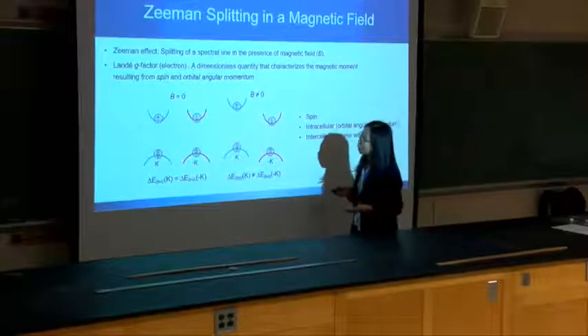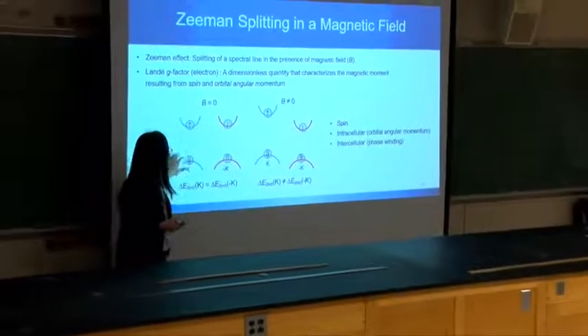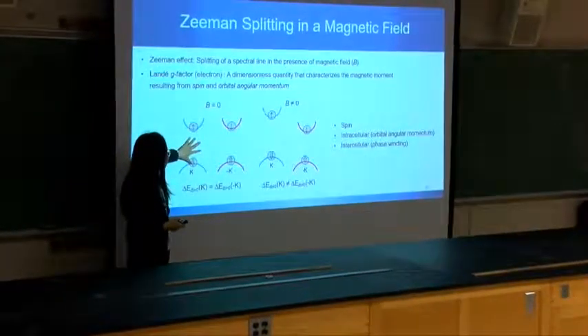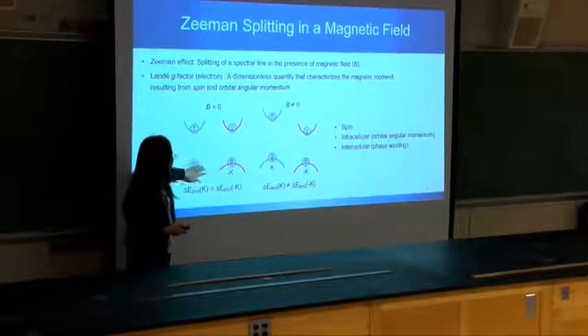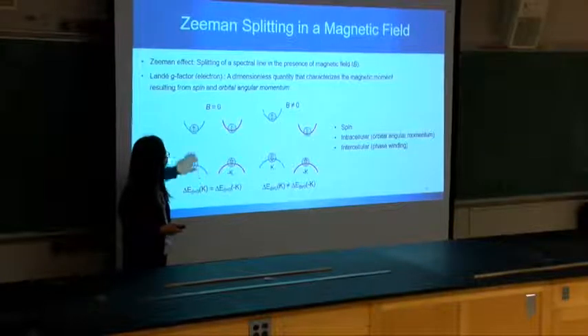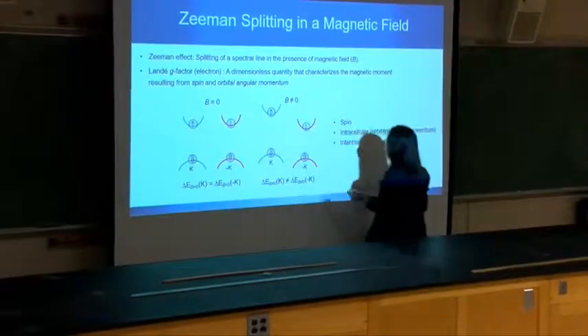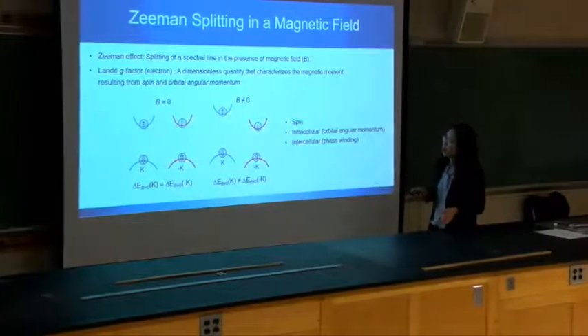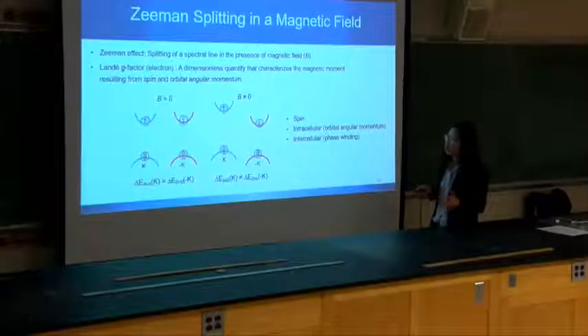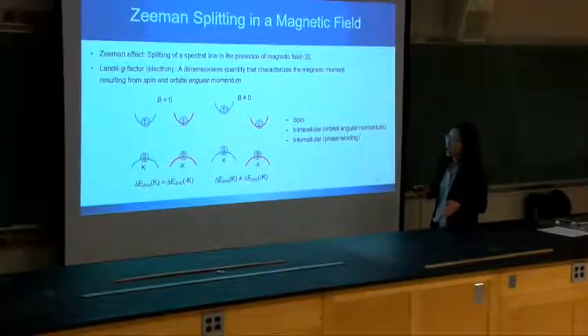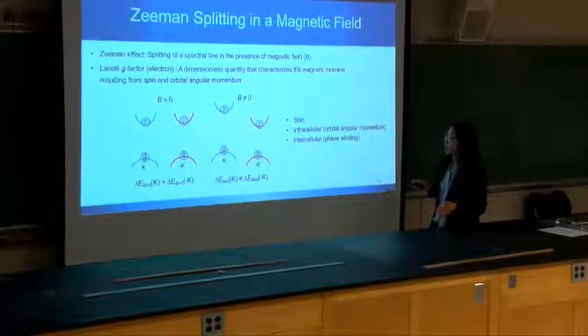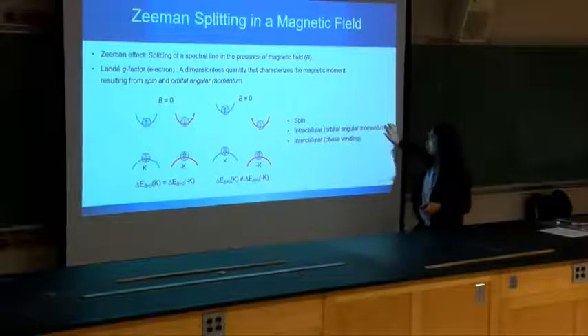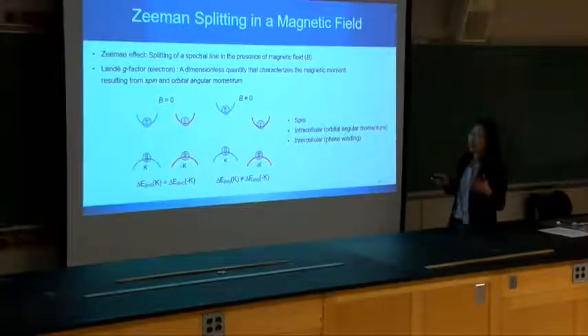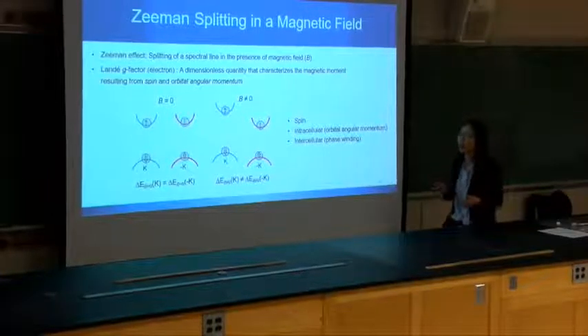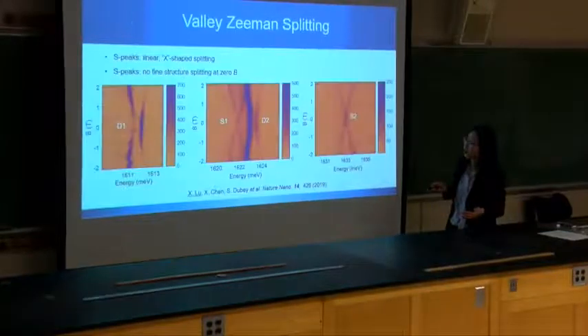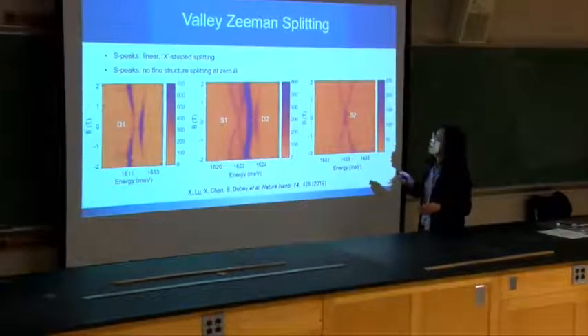Both the conduction band and valence band come from the d orbital of the metal atom, which carries orbital angular momentum of 2, and it will contribute a g factor of around 4. And the phase winding will mainly contribute for electron and hole from different valleys. If we are observing the combination from one valley, this is not so important, so it's mainly the second element here that contributes to the g factor, a dimensionless quantity that characterizes the magnetic moment.